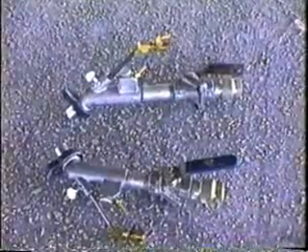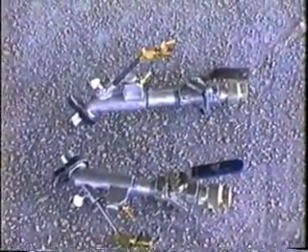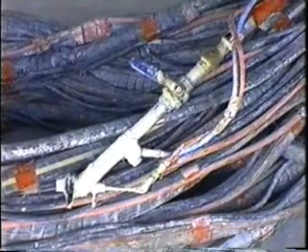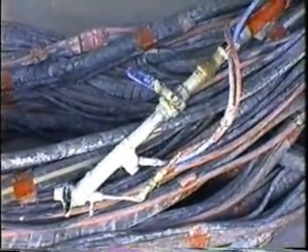The spray nozzle assembly should consist of a minimum 1 inch inside diameter aluminum pole with blow-off type nozzle cap, nozzle orifice, material and air control valves. For optimum coverage and density, a 5/8 inch inside diameter orifice is recommended.